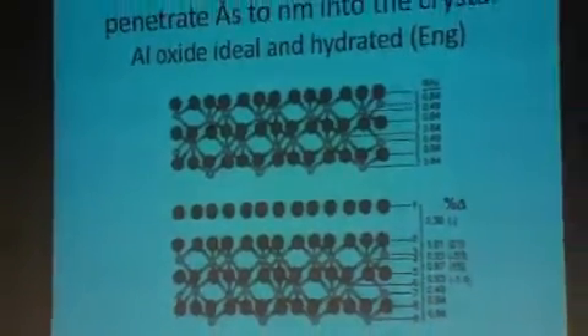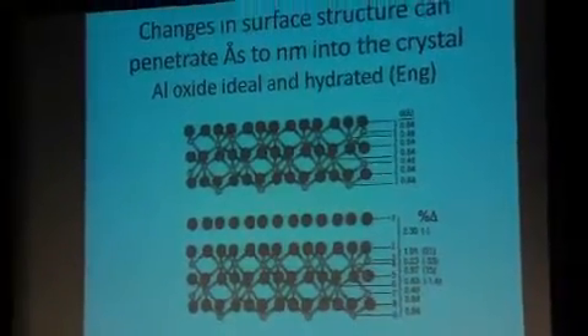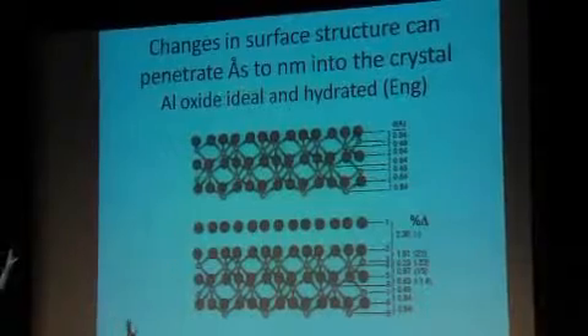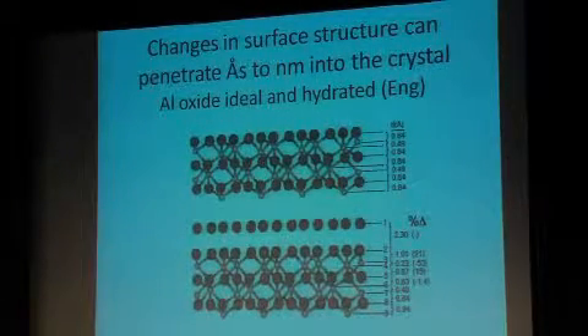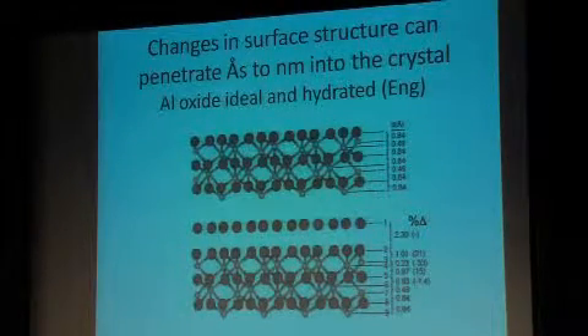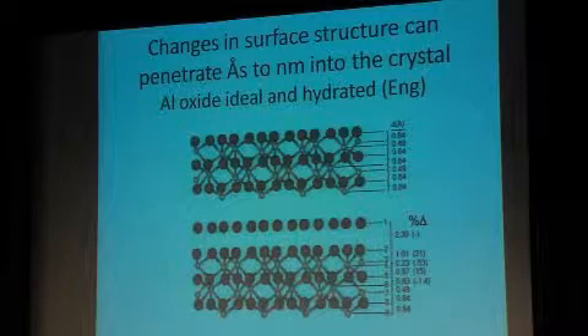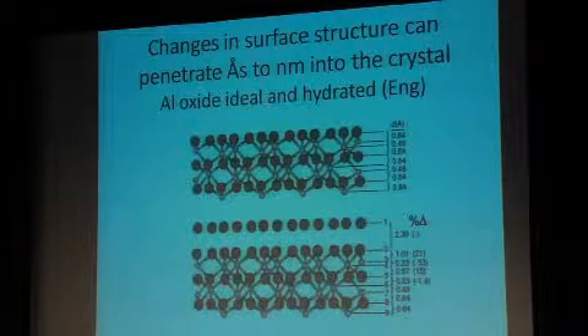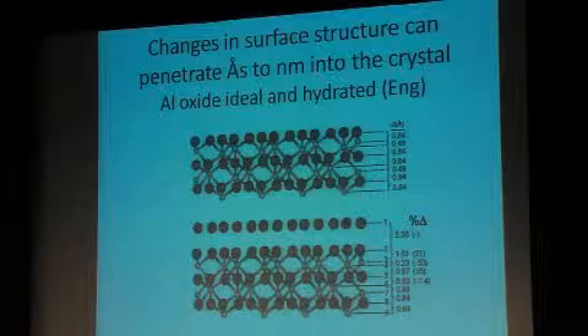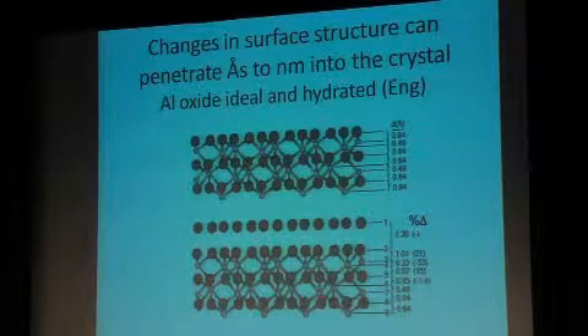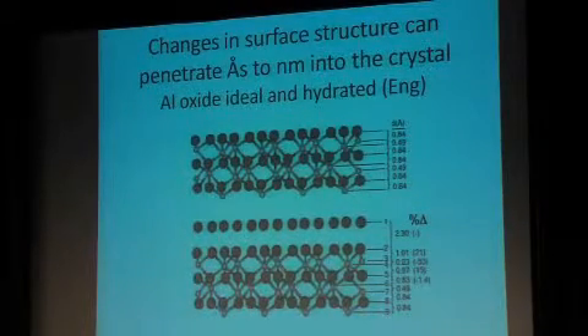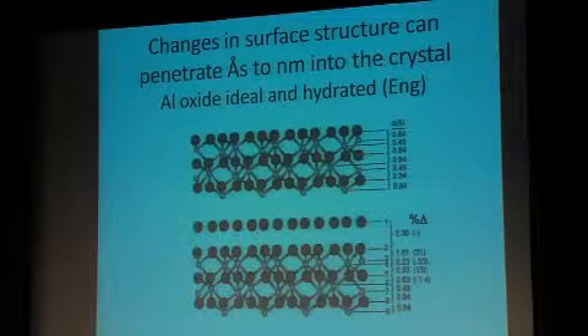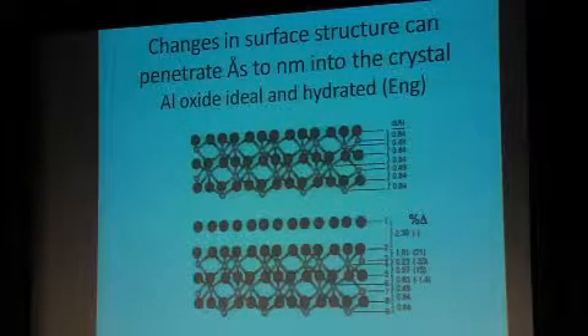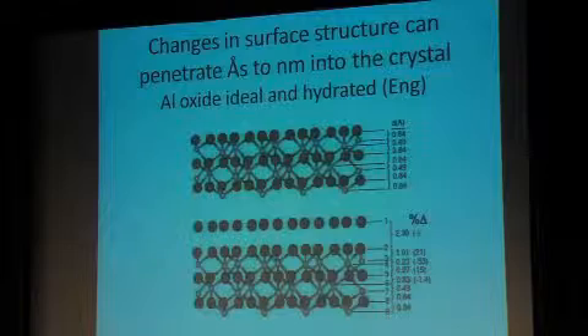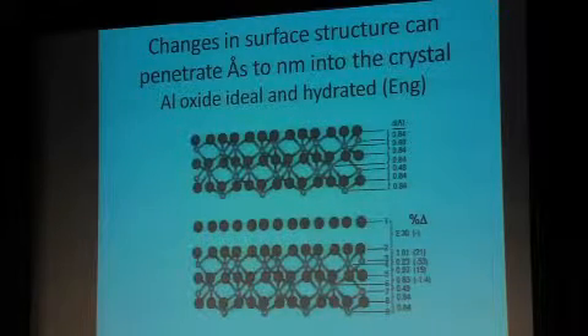Now, we've known for a very long time in dealing with surfaces that if you take a mineral, for example, this is a model, I'll go through it as a bulk structure, you can figure out very nicely exactly the coordination, where the atoms are, how they're relative to each other, what the bond lengths are, bond distances, and everything for a bulk mineral. But when you break that mineral off and it's now a surface, you've removed half of the atoms that things were bonded to. And so you now have all these dangling bonds.